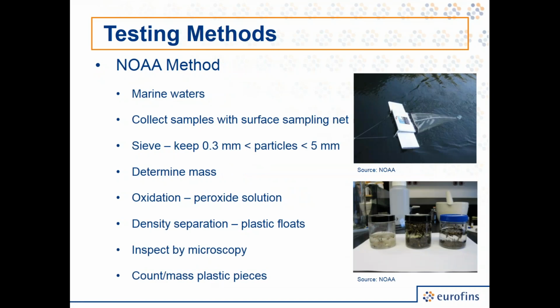Now, in contrast, the NOAA method is for dirtier waters, and the sampling sometimes is performed differently with a net. And we're typically looking at larger particles. Now, a key part to this method is that there is a chemical oxidation step to remove as much of this organic matter as possible. And this works quite well, actually, in removing practically all of the organic matter and leaving the microplastics unaltered. So this type of method is very useful for something that is dirtier in nature.